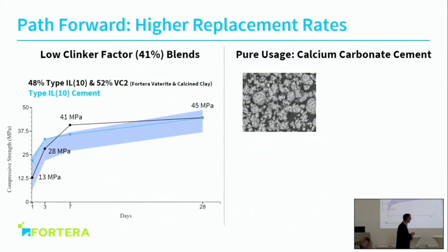What is next for us is to work on different blends, and it's on the left, especially low clinker factor blends. So this is a blend with around 40% clinker, and then a mix between our product, calcined clay, and some mineral additions. If you are interested, please contact us and we can go into more details. Really what it is about for this kind of mixes is to have higher early strengths and good flow, and these are the topics we are working further on with very encouraging results.